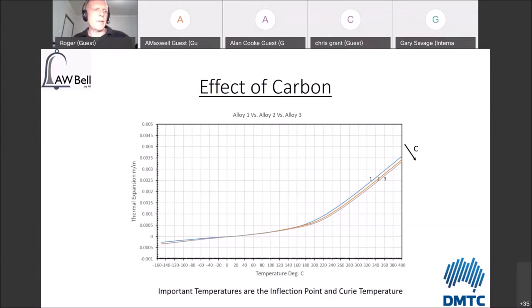One of the things that was perhaps not expected, because all of the literature tends to say that carbon is a deleterious element here, is that we actually found that as we went from about 0.02% carbon up to about 0.1% carbon, the result actually got a little bit better. Now, this is not entirely expected, but the results were what they were, and so we saw this slight improvement as carbon went up.